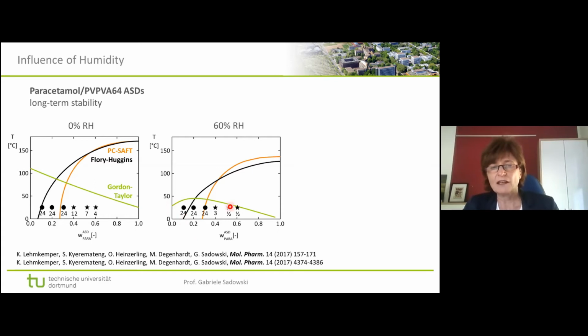And then we have, again, the samples. And you see they crystallized very fast this time. This is 2 weeks, 2 weeks, 3 months. This sample is sitting exactly on a solubility line, so it might crystallize, but at a very, very long time. These samples are outside the solubility line, so we do not expect them to crystallize ever.